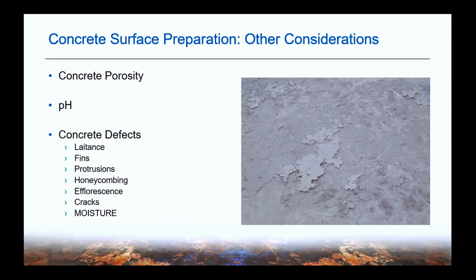So some other things to consider with concrete, first is the fact concrete is very porous. A lot of times that's caused by the air voids in the concrete. Another thing to look at, and something that sometimes gets left out, is looking at the pH of concrete. The pH of new concrete is going to be roughly 12 to 13, but to coat concrete, you really need that pH to be 9 or above. There are some methods out there to test for pH, but note that anything below that 9 or 10 pH is going to denote that there is some kind of contaminant there, or that there's been a prior chemical attack. Whatever it is that's going on there, it needs to be addressed prior to applying a coating to that surface.